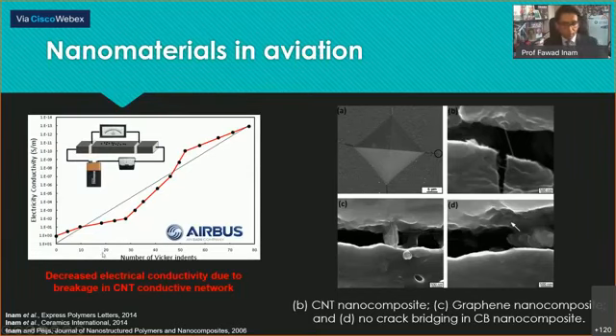What I'm showing here is a graph with electrical conductivity on the y-axis and a number of Vickers indents. Vickers indentation is a test used when you are trying to assess the hardness of a material. You have a diamond tip, and you create a notch like this, and you look at the dimensions to understand how soft or how hard the material is. What we observed by doing these indentations, so we are creating more damage by having more Vickers indents, is that the electrical conductivity is constantly decreasing because of the indentation.